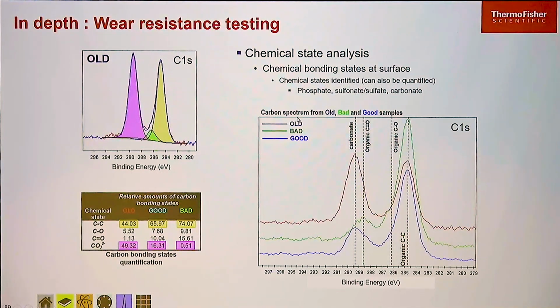So let's have a look at the carbon region. And what we can see, in the old sample, is 3 chemical states. We've got this one here, which is the hydrocarbon. We've got some carbon single bonded to oxygen. And then this is a peak due to carbonate. And if we look at the 3 samples, we can see quite big variations, particularly in the carbonate concentration.